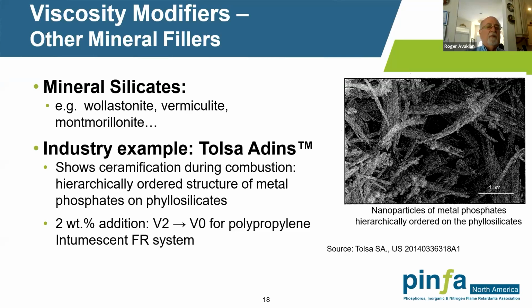According to their data, a 2% addition can take a rating from, let's say, a V2, where it's got a flaming drip, to a V0 for a polypropylene system using an intumescent flame retardant. Now, remember, as I mentioned before, and I just want to reiterate, the drip suppressants are used in combination with some sort of flame retardant, typically a non-halogen flame retardant, or in some cases, a halogenated flame retardant. Typically, the drip suppressants by themselves at these low loadings will not necessarily act as a primary flame retardant, typically used together with some sort of primary flame retardant.